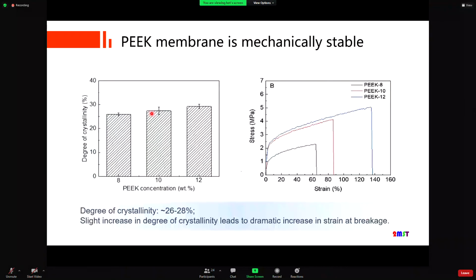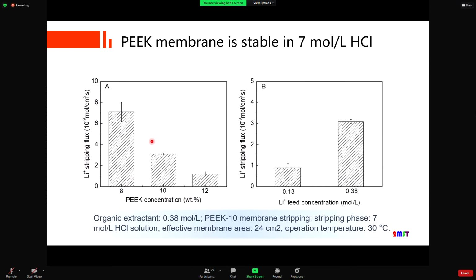So we measured the mechanical strength of the polymer membrane. It shows that there is crystallinity in the polymer. It is really strong when the 50 micron film is stretched, and the stripping of the lithium is also acceptable, but it reduced with the increase of the polymer concentration. But it increased with the lithium concentration in the brine.